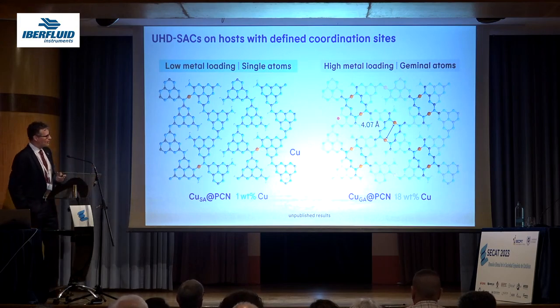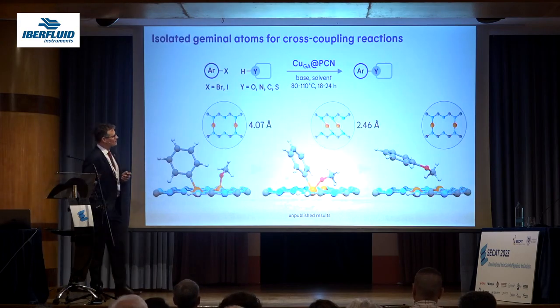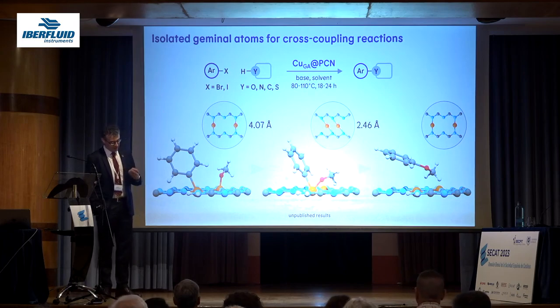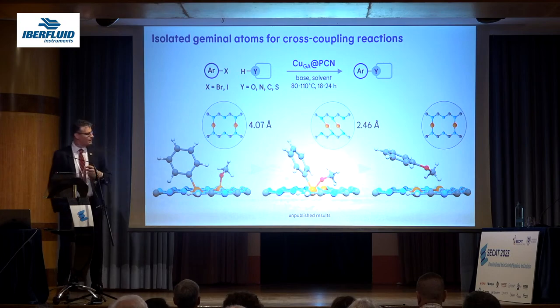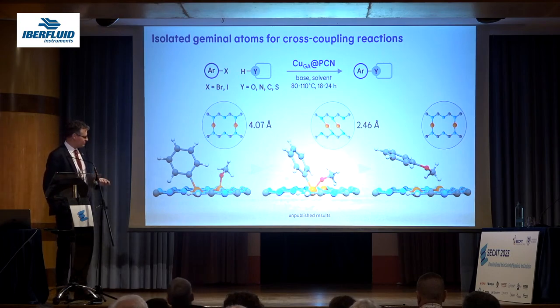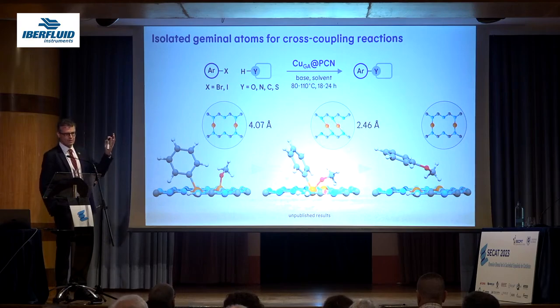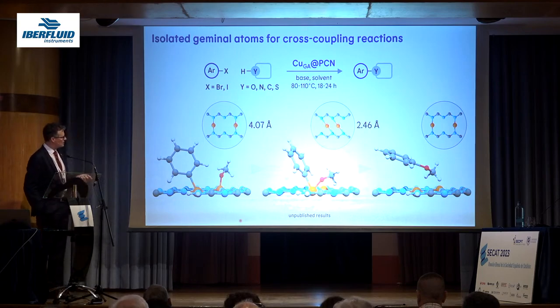And so we use these materials to produce, again, organic synthesis, organic molecules. And this is an example which I don't really talk a lot about because these results are unpublished, but I think this will be a little bit of a breakthrough in trying to replace homogeneous catalyst by heterogeneous single atom catalyst, because you see the proximity of these two copper atoms enables the coupling.